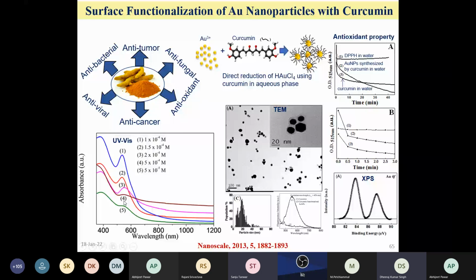And you can see that if you take the TEM, transmission electron microscopy image, this is correlated with your UV result. And in the high resolution TEM, in this closer examination, look that your curcumin molecules as an organic shell are present near your gold nanoparticle, because this black one is the gold nanoparticle, and this organic contrast difference you can say around this gold nanoparticle is where your curcumin molecules are present. So now you have successfully synthesized gold nanoparticle, where gold nanoparticles are capped by your curcumin molecule.